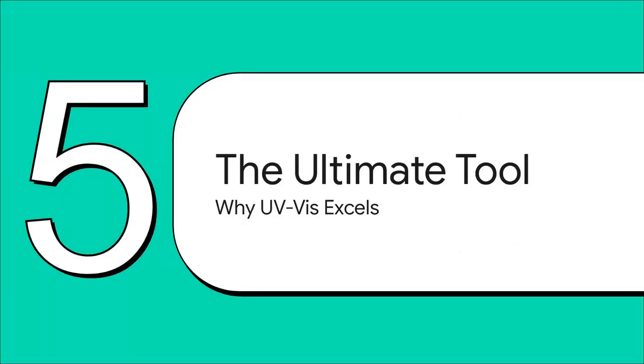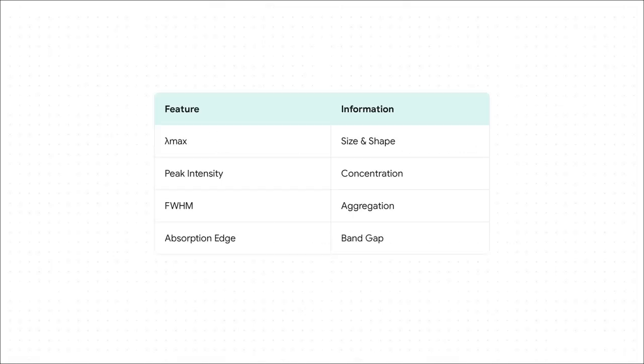Section 5. The ultimate nanotech tool. So, basically, the language of these peaks translates directly into hard physical data about your nanoparticles. Lambda max, the peak position, that tells you the size and shape. The height, or peak intensity, that's your concentration. The peak width, often referred to as the full width at half maximum, tells you if the particles are nicely uniform or if they're starting to aggregate. And finally, the absorption edge hands you the optical band gap for semiconductors. It's literally like the data curve is speaking directly to you.